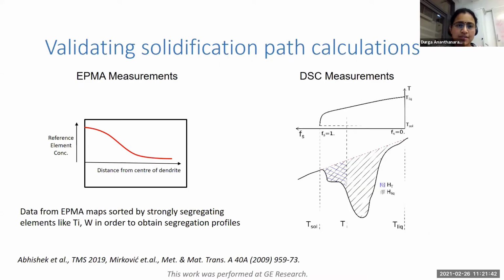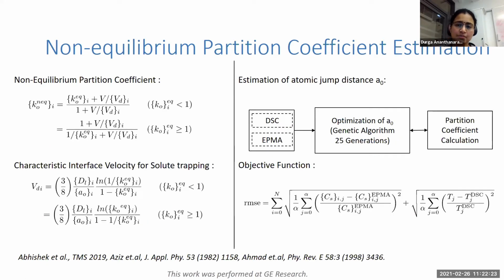So how did we validate these calculations? So we had this EPMA data. So we had maps of the full EPMA of the structure. So it covered several cells. And then we sorted this data so that we have sufficient points that represent the middle of the dendrite and the interdendritic region. And we sorted them based on known elements like titanium, tungsten, which we know will segregate to the interdendritic region. Then we also had DSC measurements, which we converted to temperature and fraction of solid. And using this, then we tried to predict using the modified Scheil approach. So going into this equation for non-equilibrium partition coefficient.